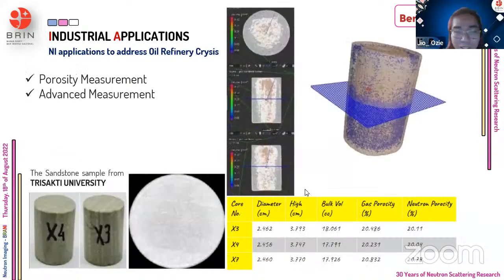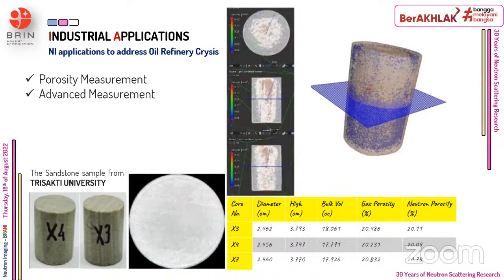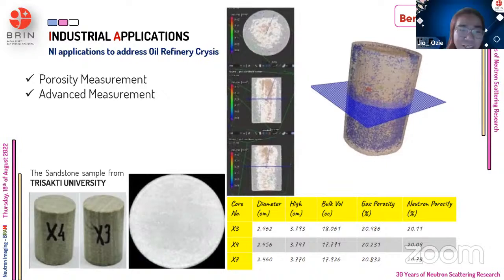And this one, when I just deal with the sandstone, sorry. Okay, this is when I just deal with neutron. This is only with neutron, but they did the measurement before with gas, because normally they use gas to measure how much gas fills the porosity, the total porosity. But neutron also did the same. And you can see that there's not a lot of difference between the gas and the neutron porosity, and you can see the pattern of the pore and the link of the porosity.